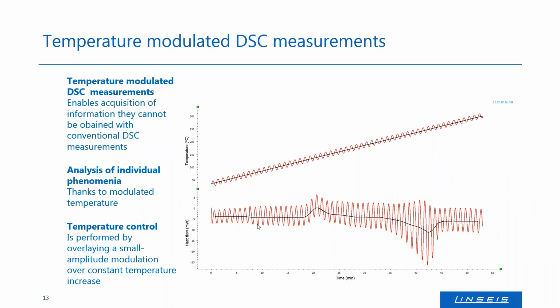At the bottom, you can see an example here. In this case, it's PET with the glass transition, the recrystallization and the melting in a raw curve. So for a conventional measurement, and the red curve here is the temperature modulated way. So this looks a bit curious here, but we will get some information through this. What we also already can see here is after the glass point, for example, the amplitudes of our results are higher. And also in the melt, the amplitude gets really high.